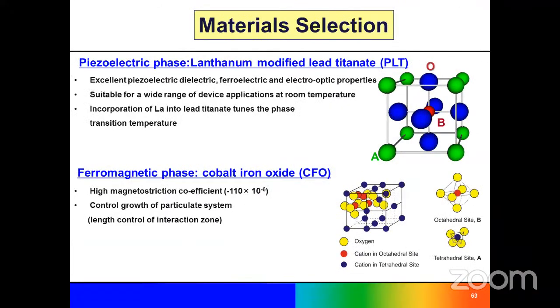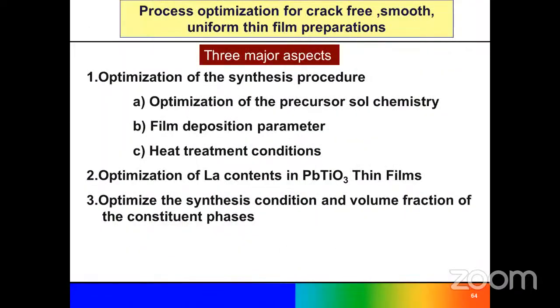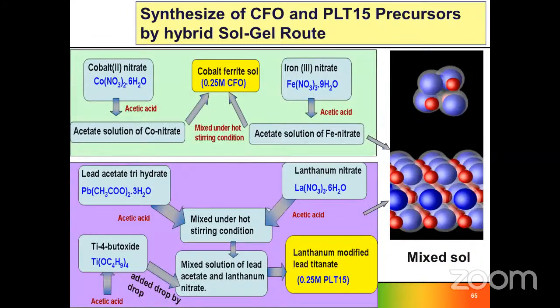Here we select as the piezoelectric material lanthanum doped lead titanate, which has a much higher piezoelectric coefficient than other materials. For the ferromagnetic phase, we used cobalt iron oxide as the magnetic material, which has a very high magnetostriction coefficient. Then we make the 0-3 type composite. For structural tuning, we optimized the sol precursor chemistry, deposition parameters, and heat treatment. Then we check the magnetoelectric coefficients.